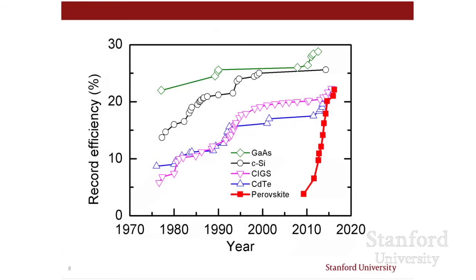But the other thing I want you to see from that curve is there has hardly been any progress in raising that efficiency since the late 90s. So that efficiency is pretty much stagnant. Above it, that's the green curve, that's gallium arsenide, and you can go up to 28% with that, but it's a very expensive technology. Right now, it's about 40 times more expensive than silicon, and I don't see a pathway for a dramatic cost reduction there.